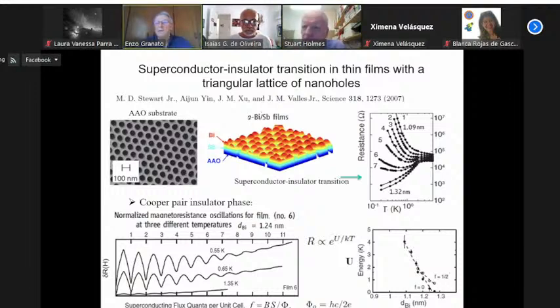But I think there are systems in which you actually see a transition from superconductor to an insulating phase with a localized insulator. I think one of these is the vortex glass, which they see if you have a superconducting film with strong disorder in a magnetic field, and then the insulating phase can actually be a localized insulator, and then you have hopping conductivity. You have a different exponent. I mean, in the hopping mechanism, the prefactor for the conductivity is quantized. So for Mott, it's 2e squared upon h. So it would fit in with your.